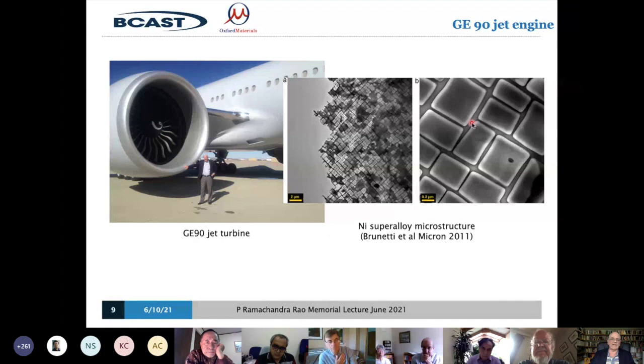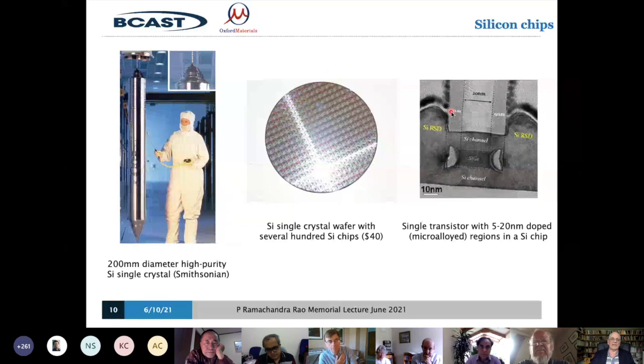Here's a 200 millimeter diameter high purity silicon single crystal. This is a wonder of modern technology, that you can grow an incredibly high purity, parts per million level purity, single crystal of silicon. They're nowadays made in sizes up to four or even five times as big as this, and then these are cut into thin discs. Here's a thin disc. You can buy this disc. I took the picture from the web. I could have bought one for $40.